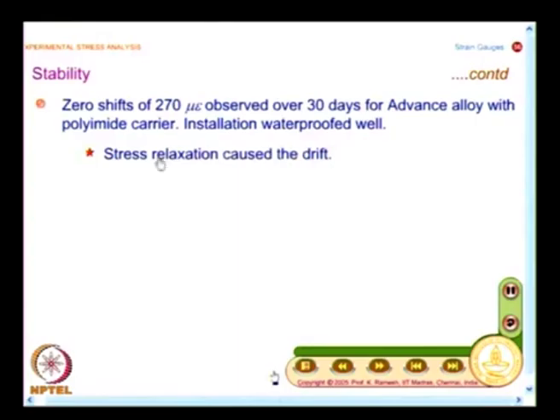And what you find here is a zero shift of the order of 270 microstrain is observed after 30 days for Advance alloy with polyimide carrier. And if you look at it, the installation was waterproofed well. There was no difficulty of moisture entering into it and deteriorating the strain gauge bonding. And what people found was the carrier is not taking the load properly. So, there was stress relaxation which has caused the drift.